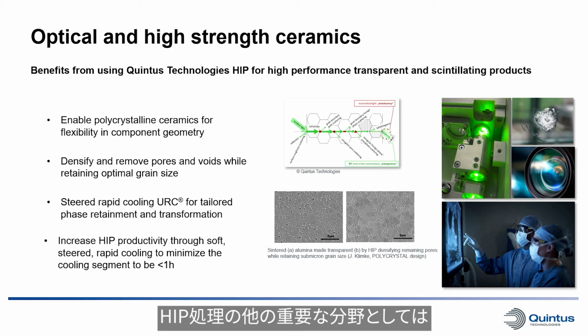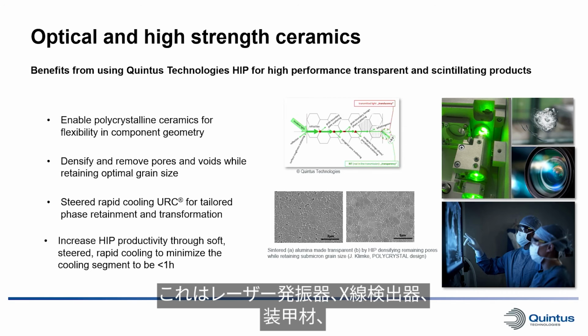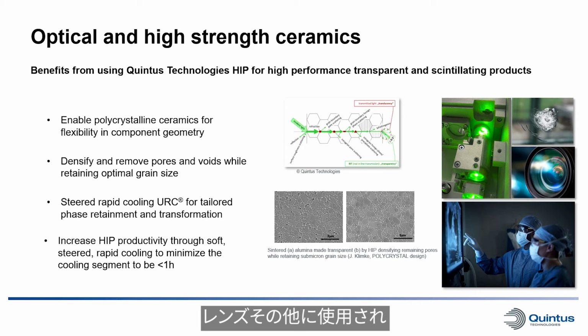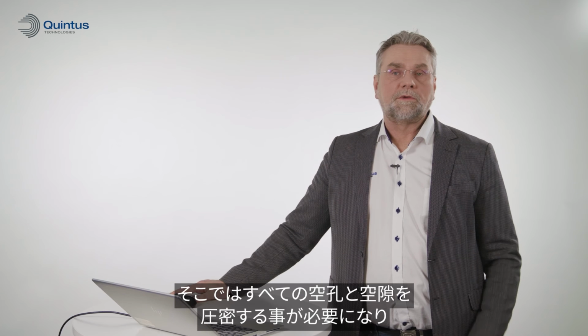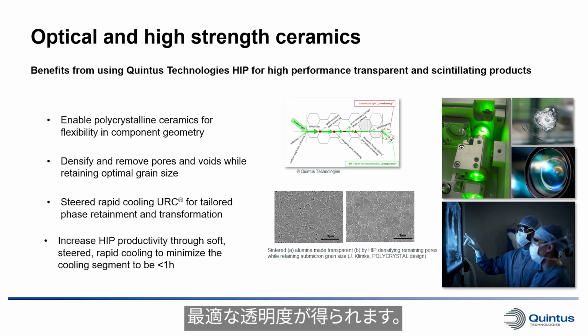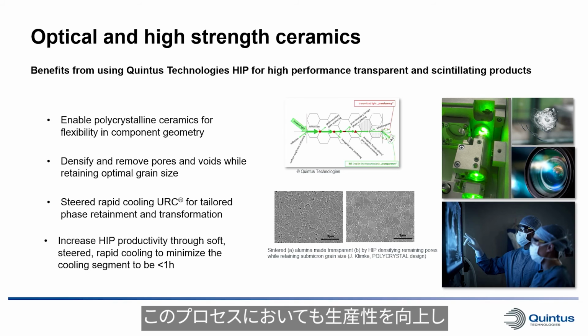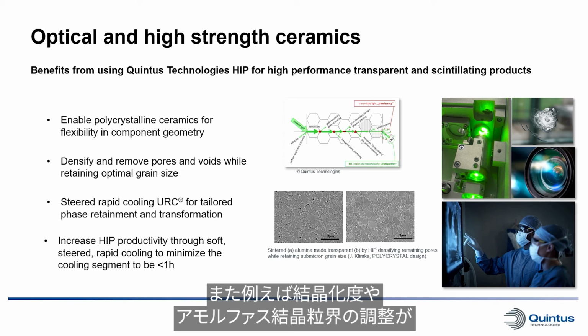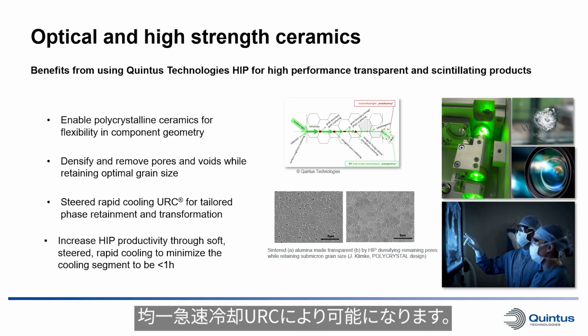Another very important area for HIPping is, of course, when it comes to polycrystalline transparent ceramics, used for lasers and detectors for X-rays, as armor material, for lenses and so on, where you need to densify all pores and voids to get down to hundredths of a percent in porosity before you have the optimum transparency. Using the uniform rapid cooling, you can of course also increase the productivity in this process, and also play around with crystallinity and amorphous grain boundaries, for instance, doing the uniform rapid cooling.